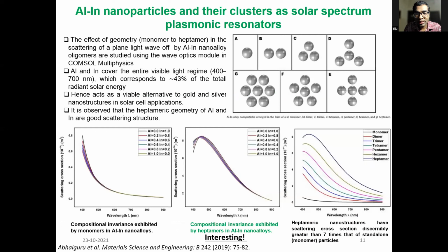All right. So this was something that we found rather interesting about aluminum indium nanoparticles. So what we did was we did multi-physics simulations, and we demonstrated, number one, that these aluminum indium particles are almost completely invariant with respect to their refractive indices when it comes to their composition. That means you could go through the full binary phase diagram in principle, and you would not see much difference in terms of their n, k values. That means the real and imaginary parts of the refractive index.